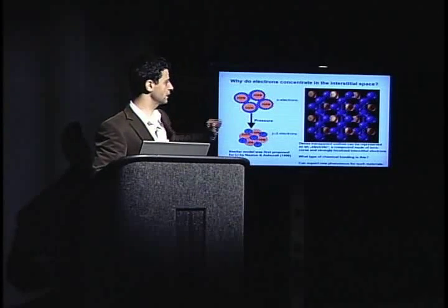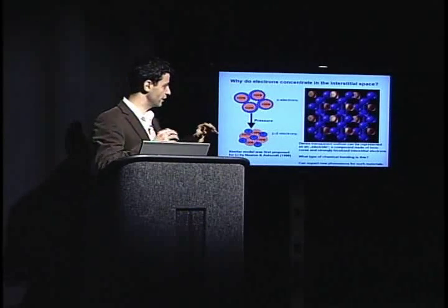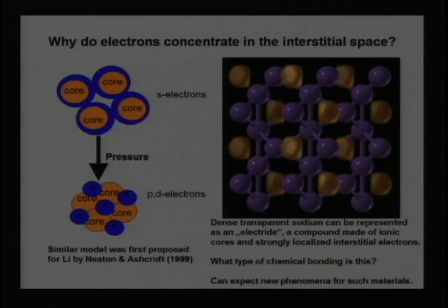What happens with sodium? Why does sodium become transparent? Why does sodium develop this maximum of electron concentration in the empty space? The model was actually proposed by Neaton and Ashcroft about 10 years ago. It does not completely translate to our case, but the spirit of it is correct in our case too. Here we have atoms at a large distance from each other at normal conditions. The distribution of the electrons is spherical, it's s electrons. Cores of atoms do not overlap. You increase pressure, cores begin to overlap, and since cores, these chemically inert regions around the atoms, repel the valence electrons, the electrons find nothing better to do than to concentrate in places which are maximally distant from the cores. They concentrate in the empty space. Since cores overlap, electrons have nothing else to do than to concentrate in the empty space.